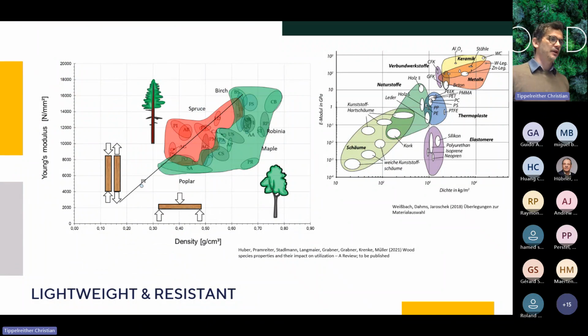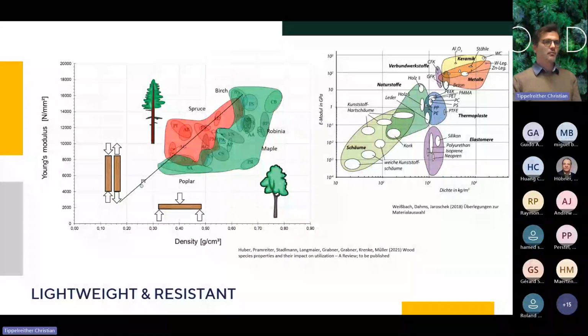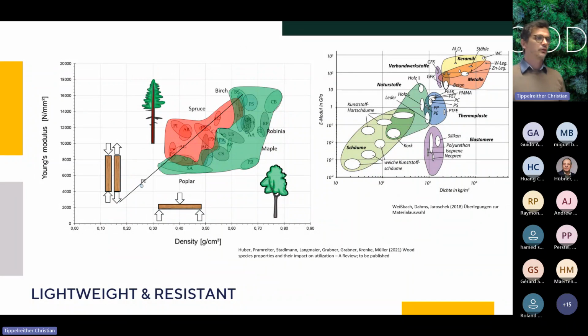And that's also a little bit the explanation regarding the theory. When you look at some Ashby maps, if you compare here the density regarding the stiffness, mainly somebody of you is a technical expert and knows, of course, ceramics, metals, or composite materials are quite on the top level regarding the stiffnesses. And when you look at the natural products, we have quite a broad variety regarding stiffness and density. But when you look at wood with zero fiber deviation, a zero fiber angle, you see that wood has quite good performance regarding stiffness compared to density, because of much lower density compared to other products.